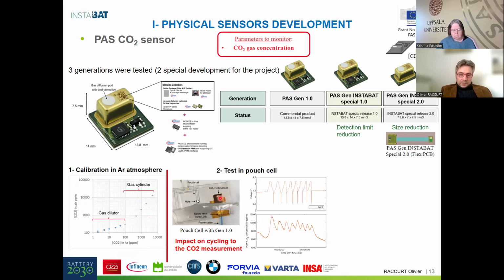Then we tested the sensor in the pouch cell with this kind of experiment, where we use a pouch cell with a small hole and the sensor just behind the cell. All this part was closed in a new pouch, and we performed some cycling. During the cycling, we saw a lot of variation of the signal from the sensor, and it's correlated to the cycling, but it's not correlated to the CO2 measurement, because there is no reason to have CO2 emission during this cycling in this case, and the concentration measurement is very, very high.